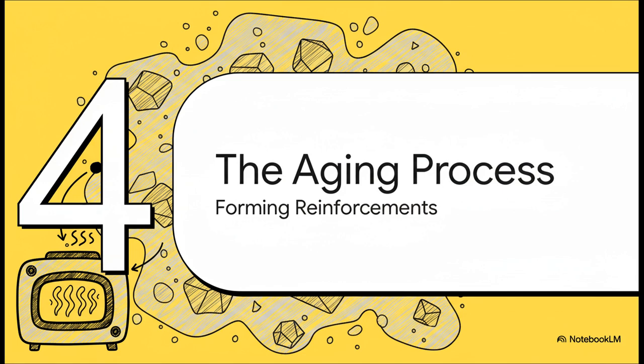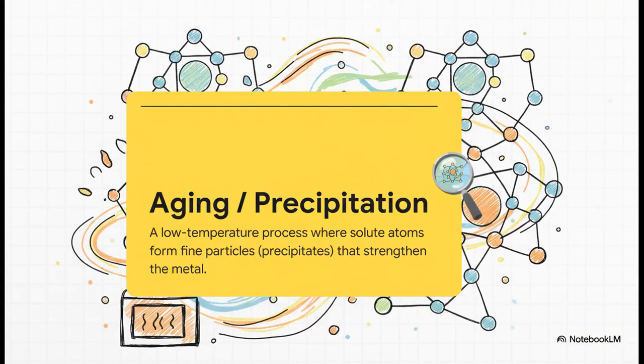Okay, so we've dissolved our elements, and we've trapped them in place with that lightning-fast quench. The material is now primed. It's ready for its final transformation. In this last step, we finally let those trapped atoms form the microscopic structures that give the alloy its truly incredible strength. This process is called aging. Now, over time, those atoms we trapped start to move around just a little bit, clustering together into these tiny, perfectly spread out particles called precipitates. These are the microscopic reinforcing bars we were trying to create all along. They embed themselves in the aluminum and they make it much, much stronger.